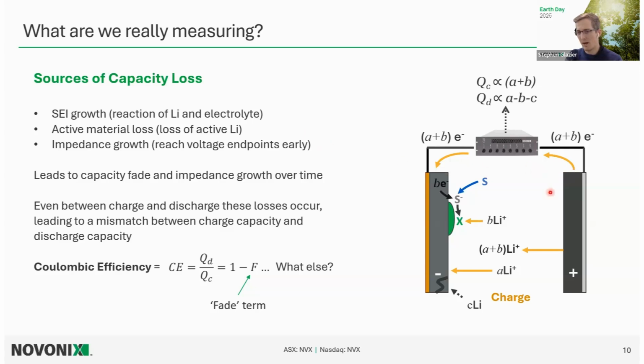And this can happen with lithium reacting with electrolyte reducing at the anode surface, consuming some of that lithium as we're charging the cell. And then as we discharge the cell, we don't get all that lithium back. So we count fewer electrons on the way back, and we can infer that perhaps we lost some capacity in the cell due to some of these capacity loss-based reactions.